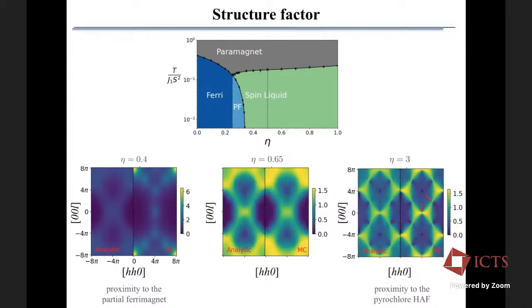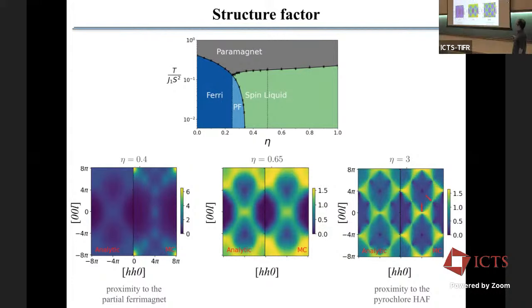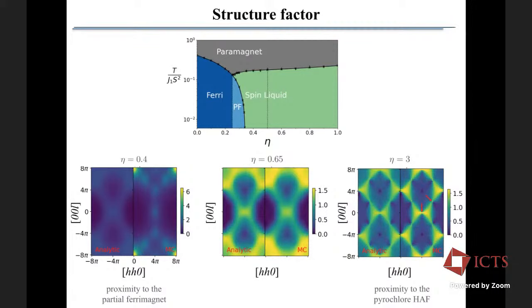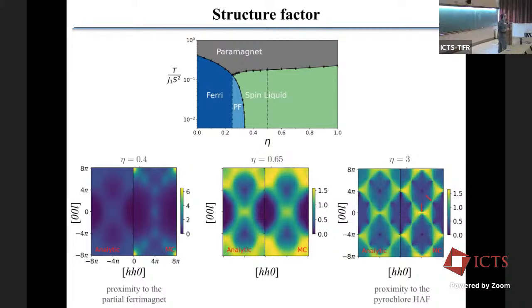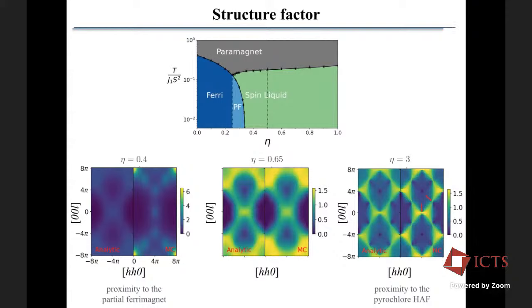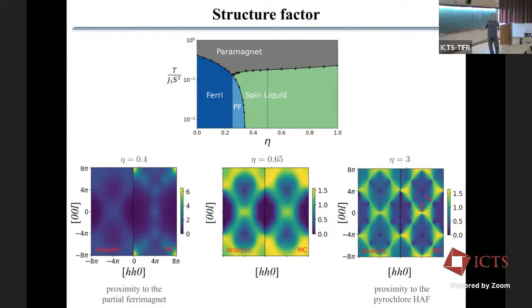Okay. Thank you. So if you are at eta equals 3, these pinch points will become broadened because of the thermal fluctuations. But when you are in this regime, this structure factor will remain qualitatively or even semi-quantitatively the same when you increase temperature, because this is all relatively diffuse. The increase of temperature will not modify the structure factor very much. Indeed. I was wondering when you go down in temperature. If you keep lowering the temperature, you still expect this to hold? Yes, these results are really at very low temperature, the lowest one we could get. When you lower the temperature, it really persists like this. I see. Thank you.